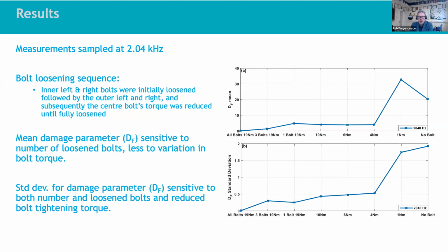Sampling at a lower frequency, 2 kilohertz, it's still possible to detect the damage parameter DF. It's still sensitive to the number of loosened bolts, but less sensitive to the variation in bolt torque. So maybe dropping the bolt torque down didn't significantly change the vibrational properties of this, so you could pick it up at these lower frequencies.